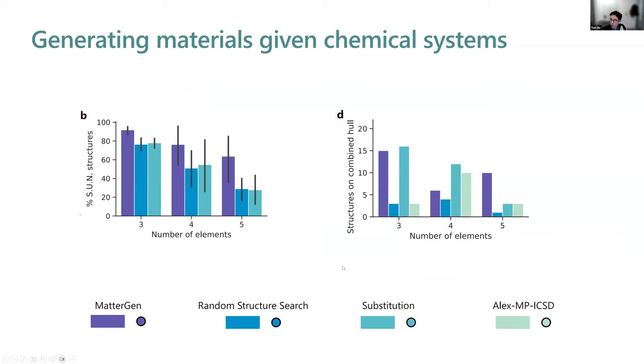So however, if you're looking at the number of structures that were on the final combined convex hull, then substitution still performs slightly better than our model for the ternary and the quaternary systems. But our model has a key advantage in the quinary, 5-element system, which actually makes a lot of sense, because now you're looking at a much bigger space, right? You want to generate better candidates. And this is where the advantage of generative models comes in.